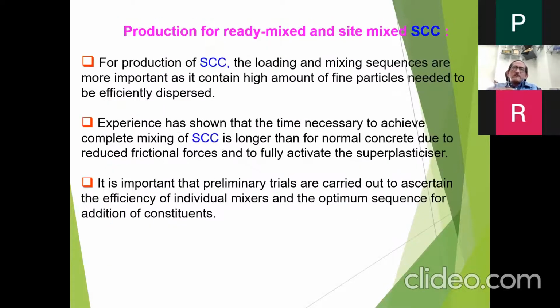Production. For production, the loading and mixing sequences are more important, as it contains a high amount of finer particles which need to be efficiently dispersed. That's why the loading time or the mixing cycle is longer. Experience has shown that the time necessary to achieve complete mixing is longer than for normal vibrated concrete, due to reduced frictional forces and to fully activate the superplasticizer. These are small things which are also mentioned here in my presentation, because this is where, without proper understanding, people nowadays claim that they are preparing self-compacting concrete, but that is not self-compacting concrete. It would be a rheodynamic concrete, or a concrete wherein only a high slump is there. That is not self-compacting concrete.